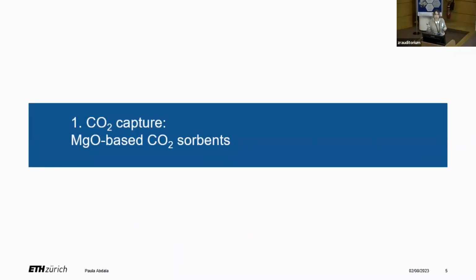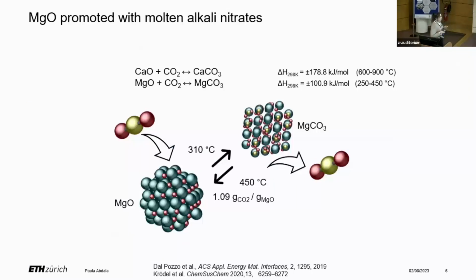Going to the first one, capture of CO2 by magnesium oxide. So we can capture carbon dioxide by absorbing it into a material on the surface, or we can absorb it via its reaction with CO2 producing bulk carbonate. For example, calcium oxide or magnesium oxide can do this job. Magnesium oxide is particularly interesting due to the temperature range where it operates, between 250 and 450 degrees. And we can swing between 2 temperatures and capture carbon dioxide and release it for further use. And this allows us to, in principle, in theory, capture about 1 gram of carbon dioxide per gram of magnesium oxide, which is quite high.